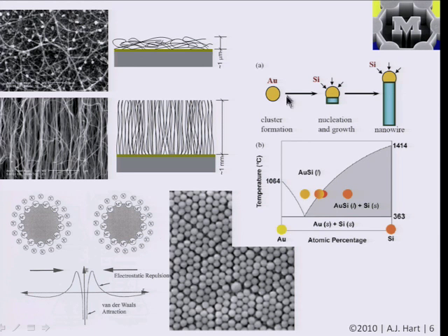Incidentally, when you make silicon nanowires, you have gold and silicon present, and silicon from the gas phase dissolves into the gold, and then you form a gold-silicon eutectic. But the location of this eutectic point at the nanoscale is lower than it would be if you had a bulk piece of material. So the idea of the nanostructures having a lot of surface lets us consider the effects